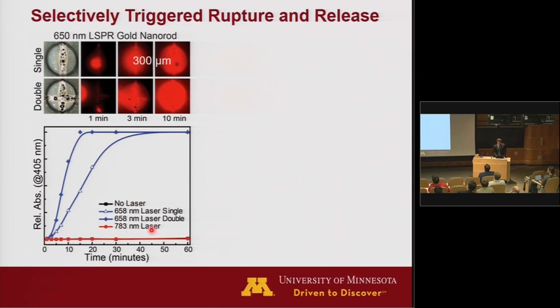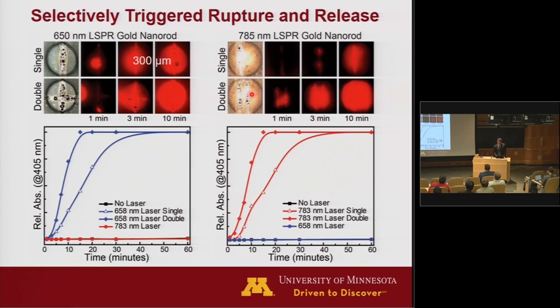Now, the trick here is that if you use a different wavelength laser that doesn't match the geometry of that rod, then amazingly you don't get any rupture whatsoever. So you really only have heating at that specific wavelength of the rod, and if you go beyond that to a different laser wavelength, you get zero release through the capsule. And the opposite is true here. If you have the other size rods within the shell and use this other laser wavelength, then you can trigger release, but if you use the first laser that worked in this case, you get no release here whatsoever. So it's a truly orthogonal system. Two different lasers, one triggers one type of capsule, the other triggers the other capsule, and they don't crosstalk during this process.